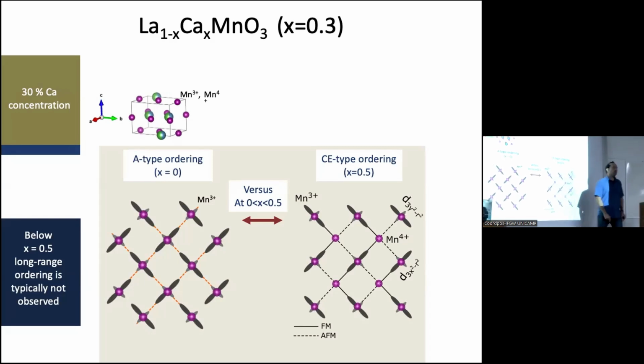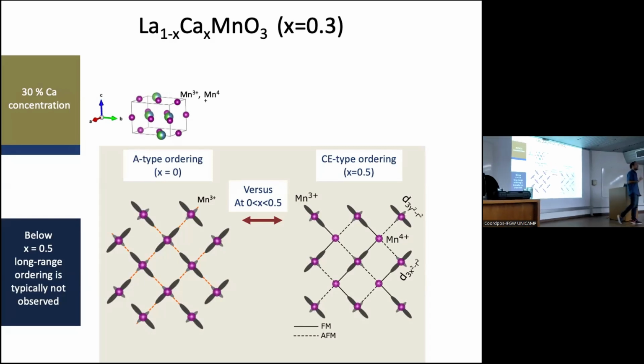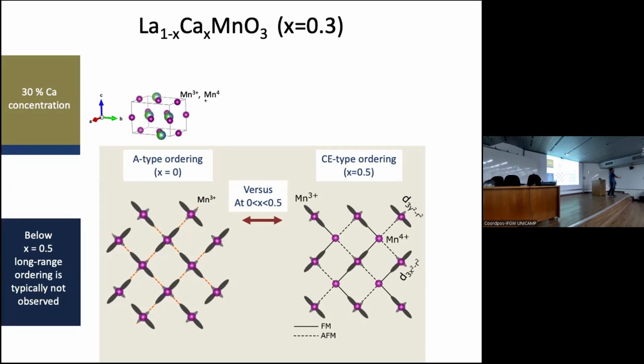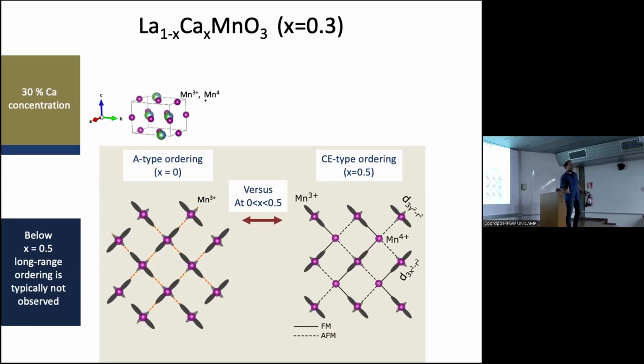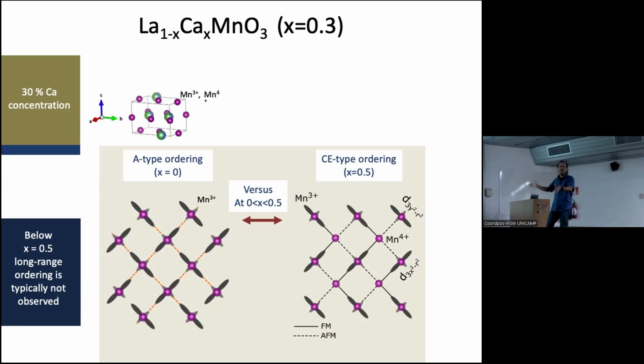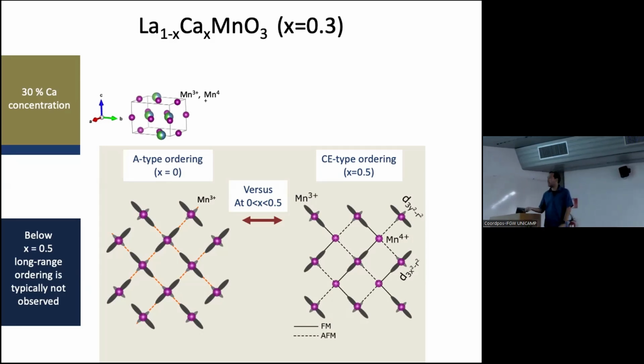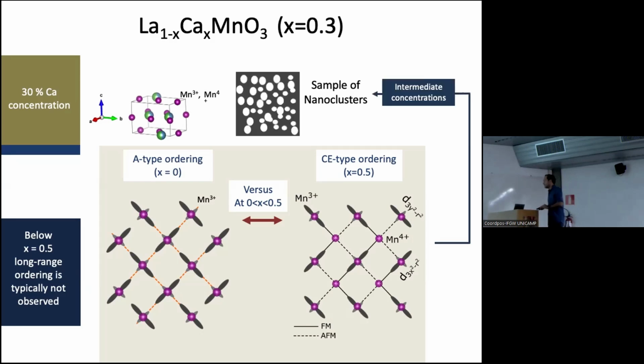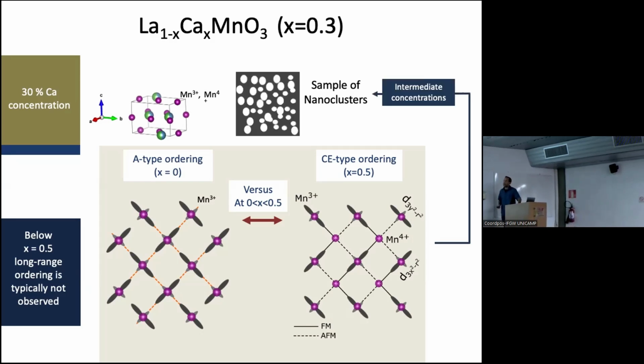When it's ferromagnetic, then by double exchange, you can have an electron that is jumping between manganese via an oxygen in between. So you can have a mobility, electrons moving through the oxygen by double exchange. So you have something that behaves as a metal, even though it's in a matrix of an antiferromagnetic material. So that's why this is interesting. This gives rise to many things.